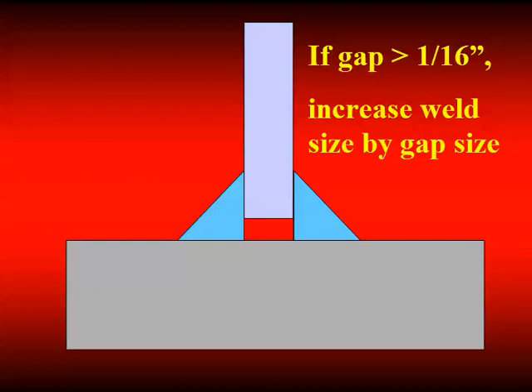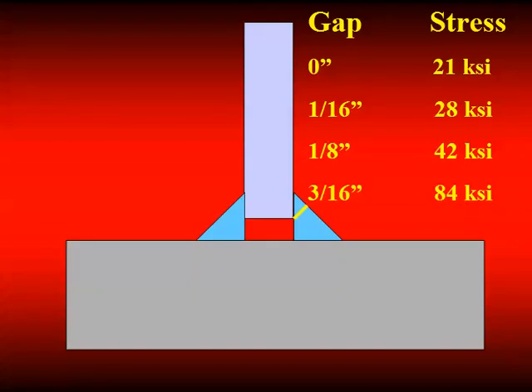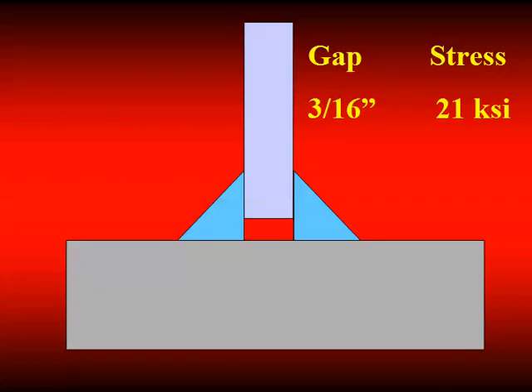Now, if you have no gap, you have 21 KSI on the throat. If you don't increase the weld size, you have a 1/16 of a gap, then you have 28 KSI on the throat. If you have an 1/8 of an inch gap, you don't increase weld size, you're up to 42 KSI. And if you have a 3/16 gap, you don't increase the size, you're up to 84 KSI on the throat of the weld. Obviously, you can't tolerate that. But if you increase the weld size by the amount of the gap, you go back to the 21 KSI.